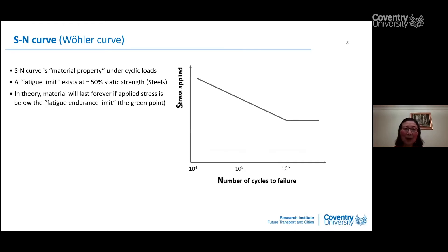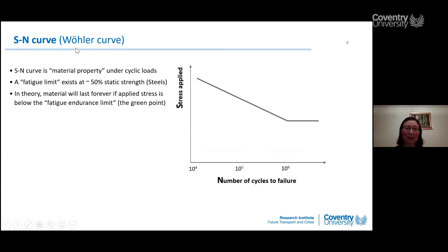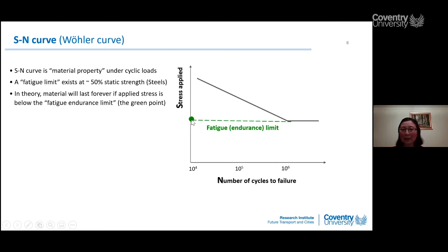The modern treatment of the Wöhler curve is called the SN curve, where S stands for applied stress and N stands for number of cycles to failure. The SN curve is a material property related to cyclic load — nothing to do with geometry. There is a fatigue limit marked as an asymptote, where the SN curve becomes horizontal.